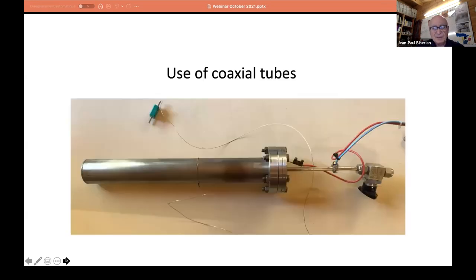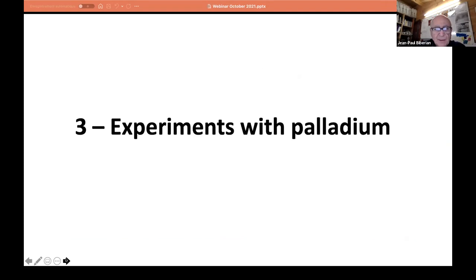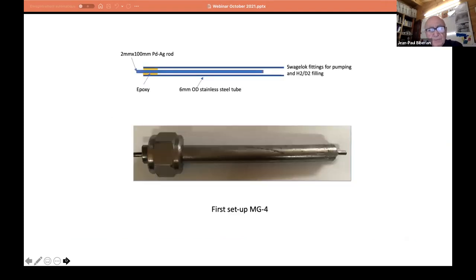So this is my experimental setup. I have a vacuum chamber. It's a CF35 flange, and the tube is about 30 centimeters long. I can introduce hydrogen, and this is the vacuum chamber I'm using. I'll show you the first experiment, which is much simpler. I took the 8 millimeter stainless steel tube, 6 millimeter in diameter. And then there was inside a 2 millimeter silver palladium rod.